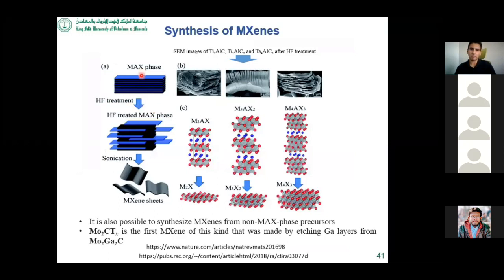Basically, the MAX phase can be treated with HF, and then this aluminum layer, or A layer, is removed, and then after sonication, these different types of sheets can be formed. You can see here various structures based on the number of carbon layers, transition metal layers, or basically the number of X layers.